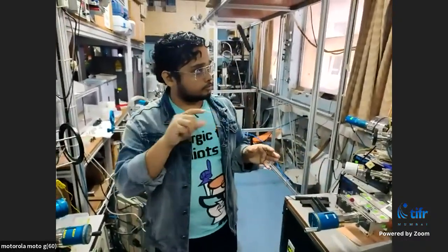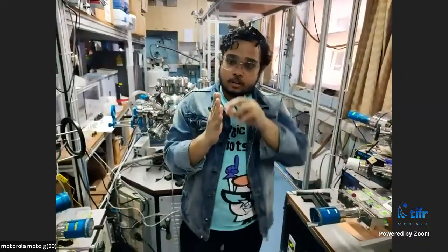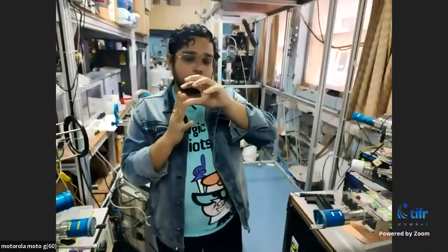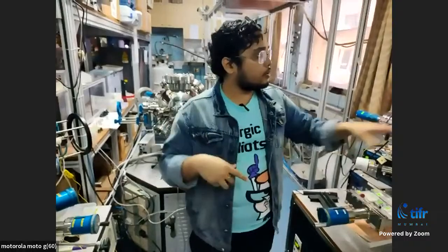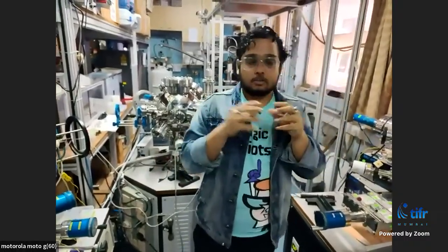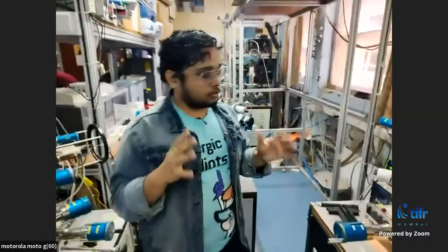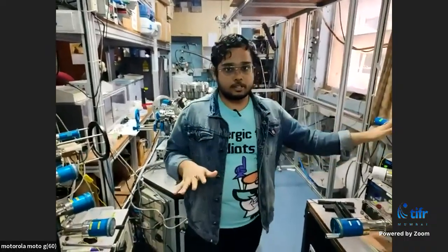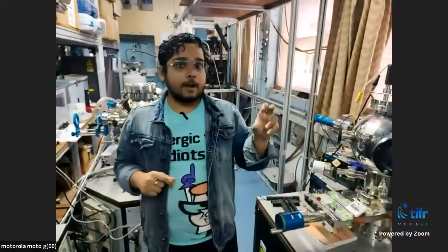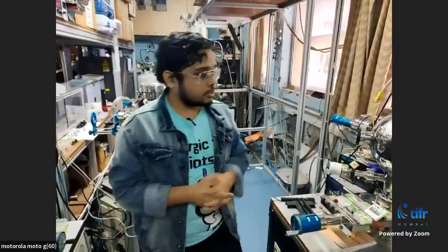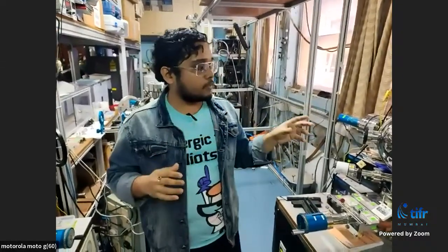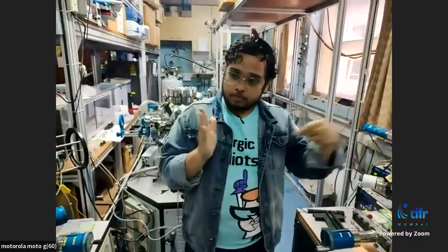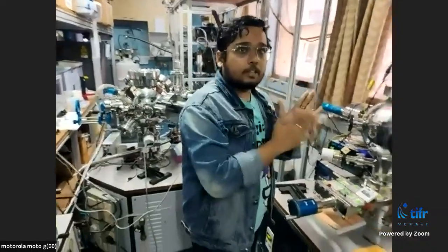Then we apply some power between anode and cathode, so that from the negative electrode, some electrons go into this chamber and react with the argon. So electrons and argon are colliding and making argon ions and some more electrons. Okay. So then we have argon positive ions and electrons in the system. And also the target, the superconducting pellet, is in the negative bias. So the positive argon attacks the negative bias, obviously. So the positive ions attack the negative superconducting pellet, and from this collision, some material from the pellet comes out, and we deposit that plasma onto the substrate, and we can make the thin film.